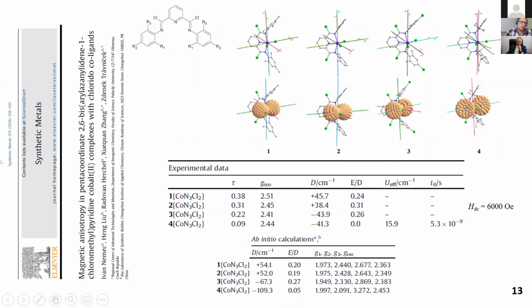One more interesting work was presented here, and the authors changed, substituting this big ligand, and they were successful in changing the D value, the zero field splitting parameter, from positive to negative. And this work looks like our results, where we switch the value by magnetic dilution for a mononuclear cobalt complex.